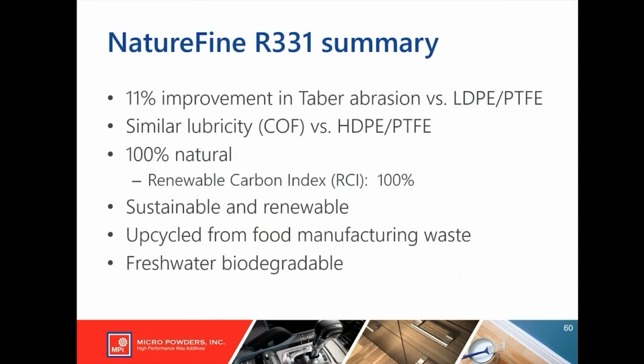So in summary, it actually has about 11% better Taber resistance than the best synthetic, in this case a PTFE-based composite powder. You get similar lubricity versus a high-density polyethylene PTFE powder. It's 100% renewable, and people are now starting to talk about a renewable carbon index, or RCI. And this material has an RCI of 100%. It comes straight from the plant. It's extracted and purified with food-grade ethanol, for that matter. So there are no harmful solvents used in the processing. Sustainable and renewable, upcycled from food manufacturing waste, and freshwater biodegradable.